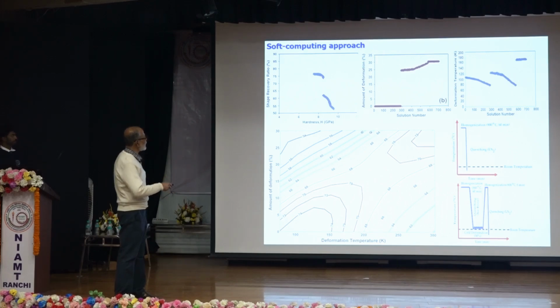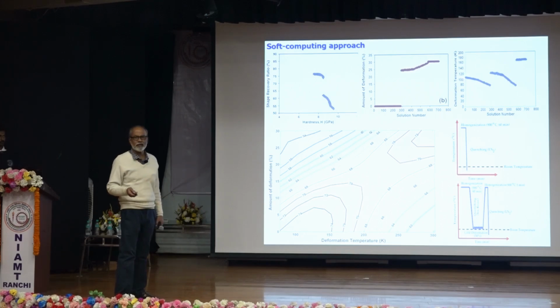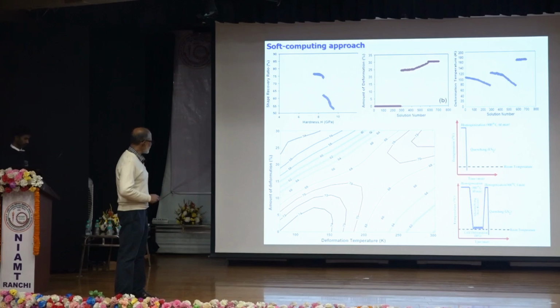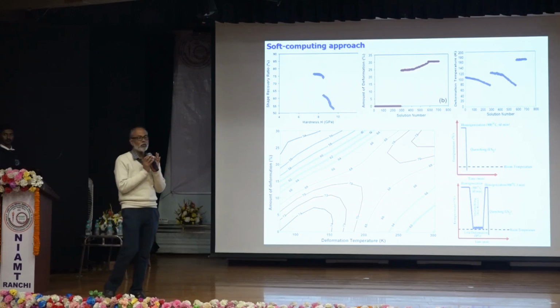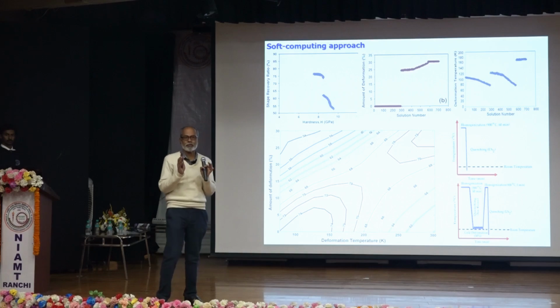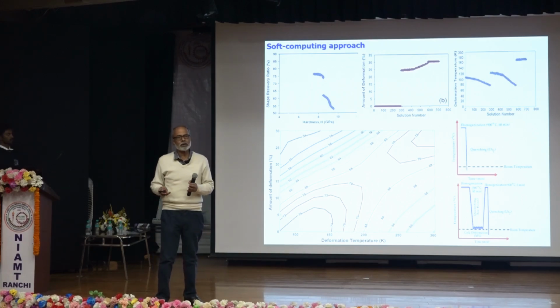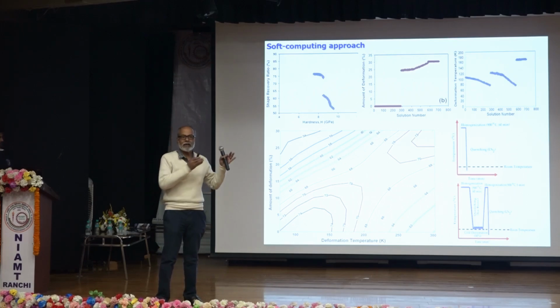We found that deformation doesn't contribute much as we analyzed the data. Similarly, a deformation temperature below 100 K is not very effective, which we didn't find when we were conducting experiments. So we created a contour of shape recovery value against amount of deformation and temperature. We found that the maximum recovery value concerns a deformation temperature of around 100 K and a deformation amount of 0 to 5. The whole experiments were almost unjustified, and I was really scared about the future of his PhD after conducting so many experiments. We could not conclude anything significant except we could correlate the microscopic and macroscopic behavior.